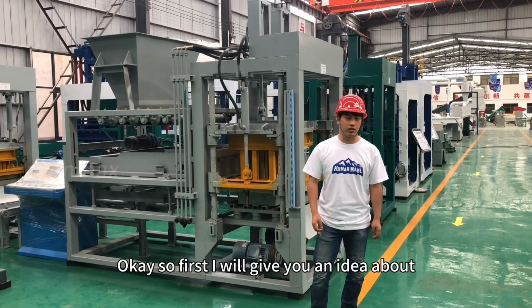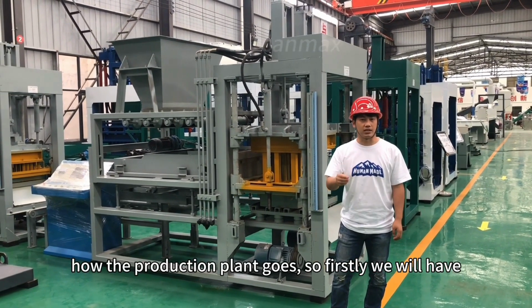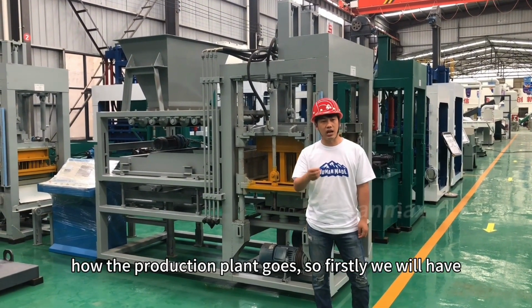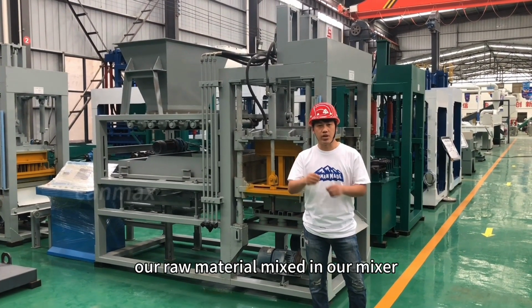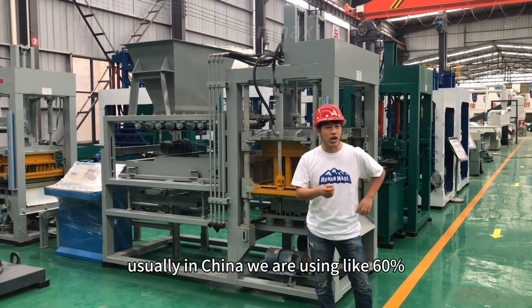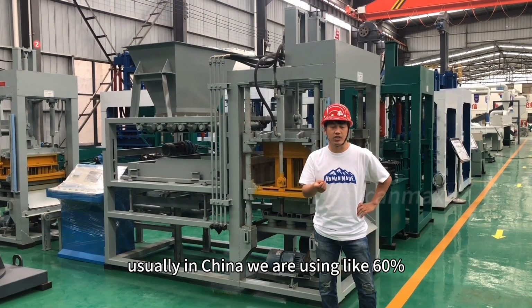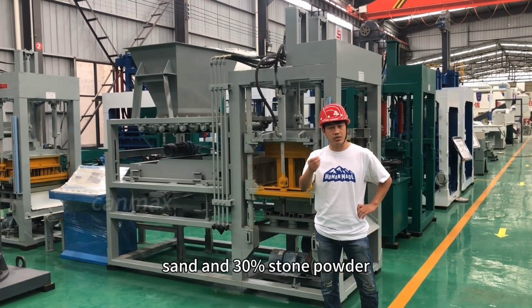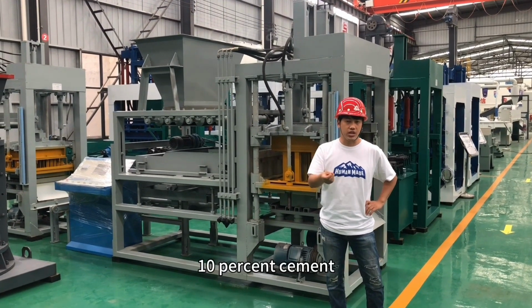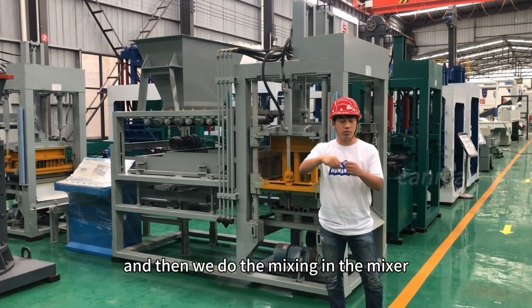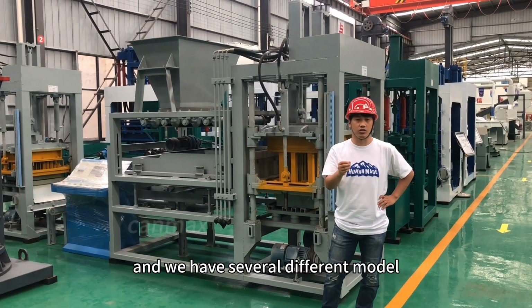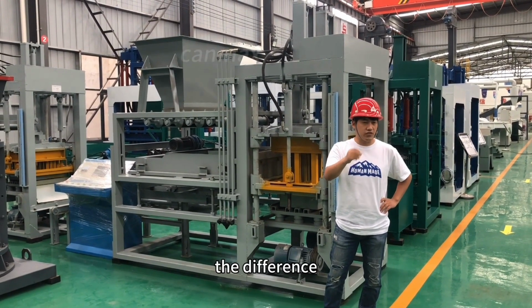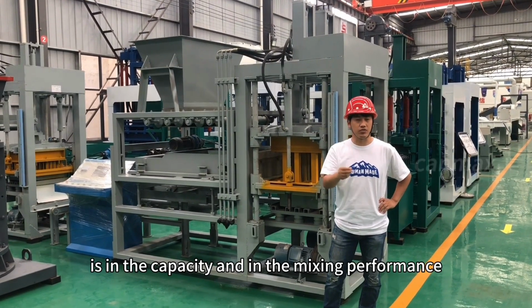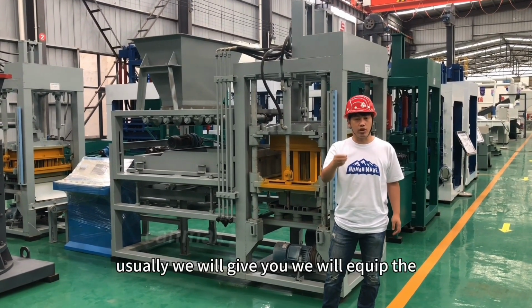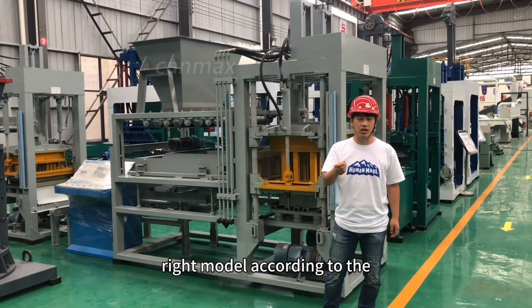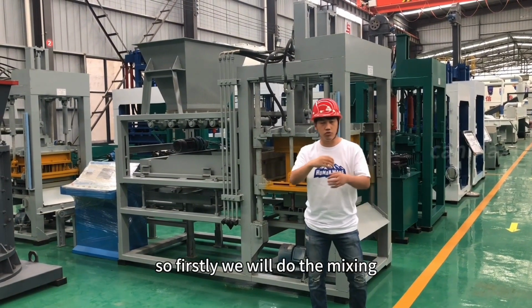Okay, so first I will give you an idea about how the production plant goes. Firstly, we will have our raw material mixed in our mixer. Usually in China, we are using about 60% sand, 30% stone powder, and 10% cement, and we do the mixing in the mixer. We have several different models of mixer, and the difference is in the capacity and the mixing performance. Usually we will equip the right model according to the block machine. So firstly we will do the mixing.